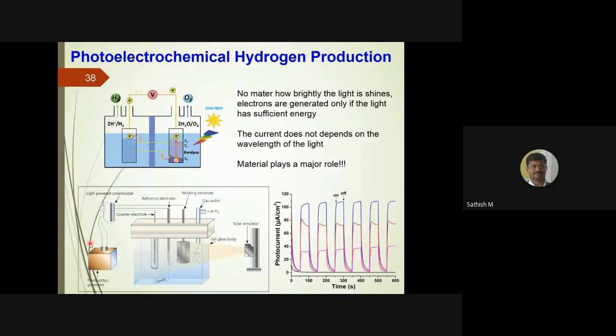What you are doing is you have a counter electrode, you have a reference electrode, and then the working electrode is your semiconductor based or photocatalyst based material. When you shine a light, you will apply some bias potential. Okay, that means some minimal energy you are giving to the system so that this reaction takes place quickly. So here that is what the electrochemistry plays. In most of the cases, the bias voltage will be 0.2 or 0.3.